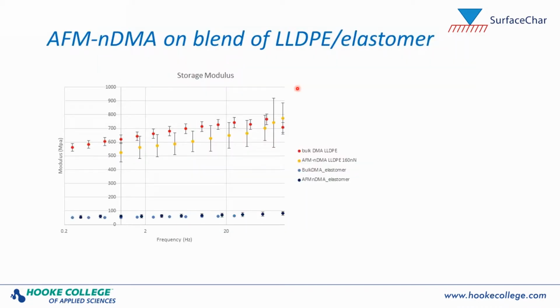Here is some more data comparing the AFM nano DMA on a blend of linear low density polyethylene and an elastomer. And this is looking at the storage modulus. So here is the polyethylene data, here is the elastomer data, and we can see here in red is the bulk polyethylene, here in orange is the AFM nano DMA, and at the bottom here the bulk DMA for the elastomers is in light blue, and dark blue is the AFM nano DMA measurements.